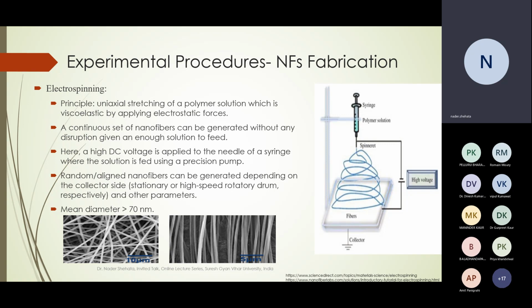You can control your formed nanofiber. So the principle of electrospinning is the stretching of the polymer in a uniaxial direction, depending, as I said, on the viscosity of the solution, and under applying electrostatic force coming from the highly exposed electric field. Then a continuous set of nanofibers could be generated, hopefully without disruption, given enough solution to feed, or we can have some troubles with these nanofibers, including the formation of beads, for example, or discontinuity in the formation of nanofibers.